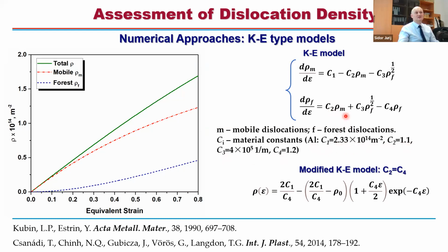Right, all you need is to put these constants into this equation, and then you can easily calculate the amount of dislocation, mobile and forest dislocation. So for mobile and forest dislocation, you can see their evolution, and here is the total dislocation density. For the modified model, basically what people observed is that C2 and C4 parameters are almost identical for the majority of materials. And then if you assume that they are identical, you can find an analytical solution, which you can see here. And then you can directly calculate the total dislocation density in different materials, depending on the amount of strain.